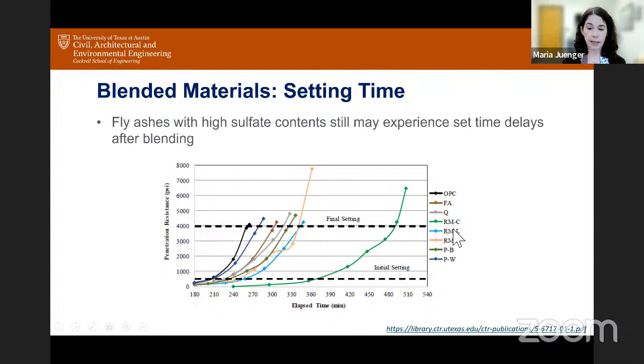So these are 3 different fly ashes that have been remediated, in this case by mixing with a natural Pozzolan, so you can change their composition. And by changing the composition, you can meet a specification. If you look at setting time, the thing that draws your eye in this picture is this crazy green line.